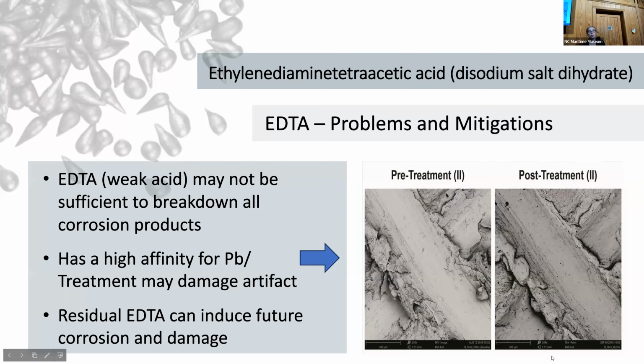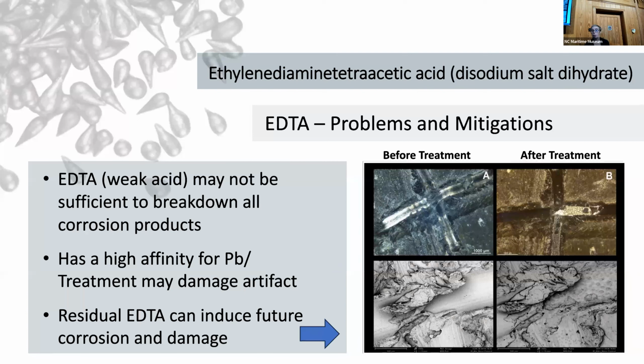You can see there has been some polishing of the surface, some erosion essentially of the surface from the treatment process. And this is another example from that data set in which we did have a few instances where we did get some renewed corrosion products forming. You can see these little pits right here because there's still some residual acid that was left on the surface and it wasn't rinsed thoroughly enough.